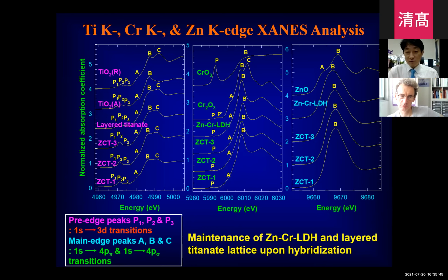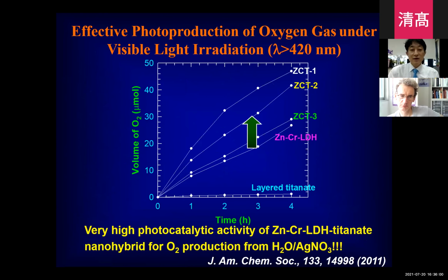Also from the zinc K-edge XANES spectra, we observe the typical spectral feature of the LDH. So from that, we can confirm the maintenance of the zinc chromium LDH lattice after layer by layer ordering. There are many experimental evidences, but I skip them. But the resulting material shows very promising visible light photocatalytic activity for water oxidation.